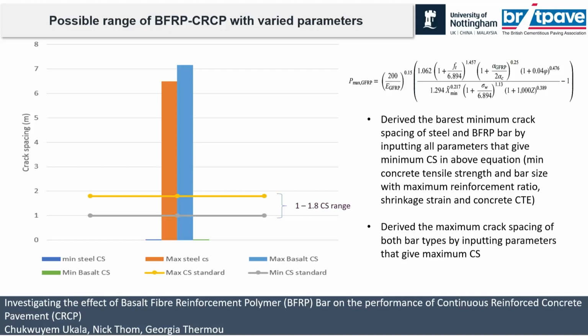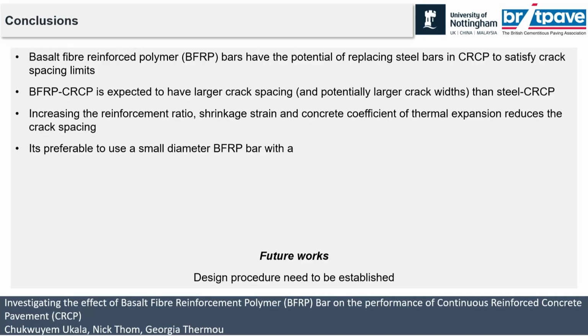So what it means is that, theoretically, between a value here and a value here are all possible crack spacings for the basalt, for the steel, and for the model using the basalt. And from what we have seen so far, we expect our model, or the reality of the basalt, to fall somewhere in the middle of this. That concludes that we can get the desired crack spacing with our basalt bars in CRCP if we can use our models or tweak our models to give us the kind of value that we may need. So that is part of our conclusion.